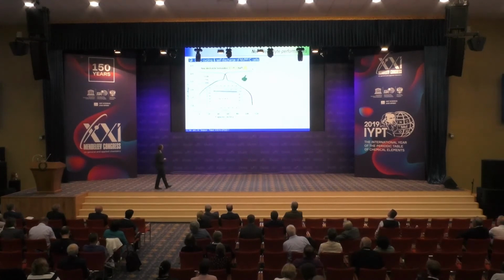So we have done a large amount of theoretical and experimental work, and we come out with, in this case, this electrolyte, EC-PC, with these magic cocktails that I will call, because we have 4 types of additives that are here together, and it's by their synergy that they can really improve the performance. And indeed, we could improve the performance. This is, in this case, what we could reach at 35 degrees C, where you can now nicely see the superimposition of voltage-composition curves and the nice capacity retentions.